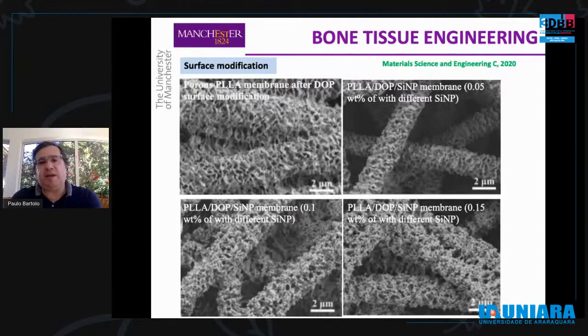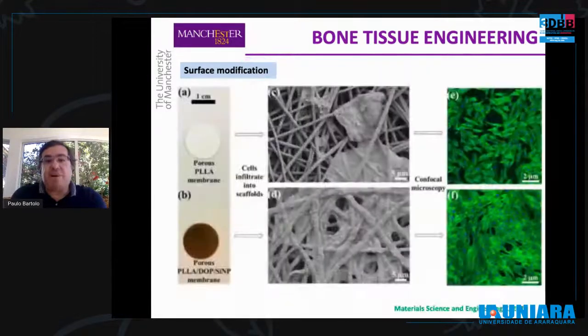The structures were coated with silica nanoparticles, and the reason for using silica nanoparticles was due to the high surface ratio of the silica nanoparticles and also the biocompatibility of these particles. This coating mechanism increased the strength of the construct and also the hydrophilicity, and the structures were also doped with dopamine, not only to increase the cell adhesion and spreading, but also the strength of the silica nanoparticles on the structure. And as I mentioned, in all cases, the PLLA meshes and the treated meshes were able to support cell adhesion and proliferation, but much better results were observed with the structures modified with this method.